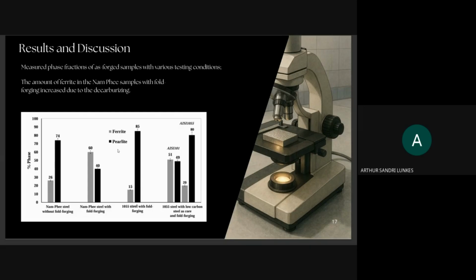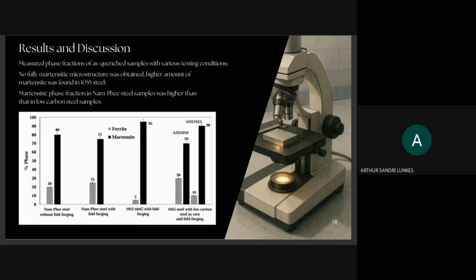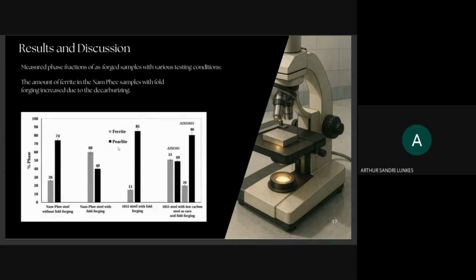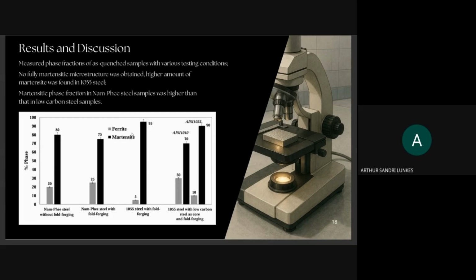The highest pearlite structure is the 1055 steel with fold forging. It's okay because it has more percent of carbon. It's interesting. Now we have ferrite and martensite, so it's for the quenched process. This one here is only forged, and this one here is the quenched process.